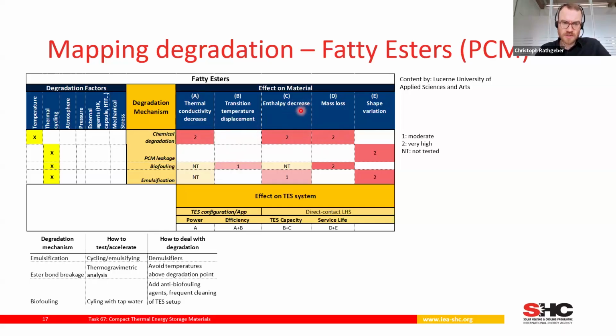For example, if we look at effect number C, enthalpy decrease, that will in turn have an effect on the performance of the TES system, for example, on the TES capacity. So here we also see a direct contact latent heat storage system that was tested by Lucerne University of Applied Sciences and Arts.